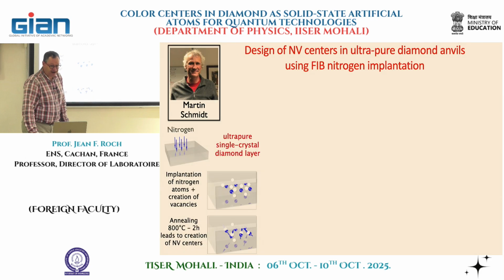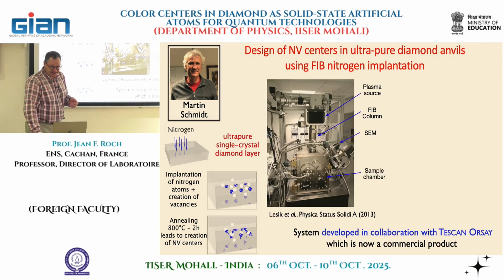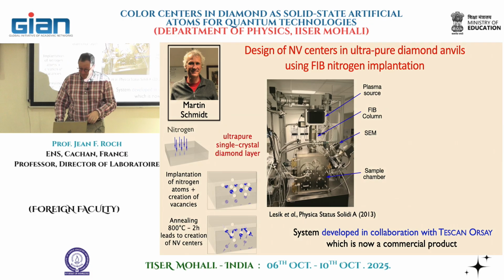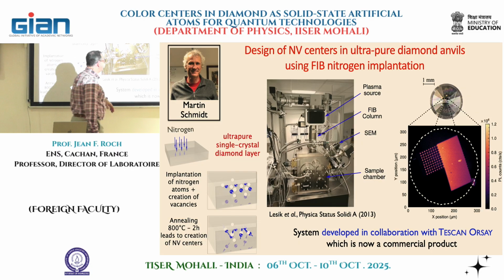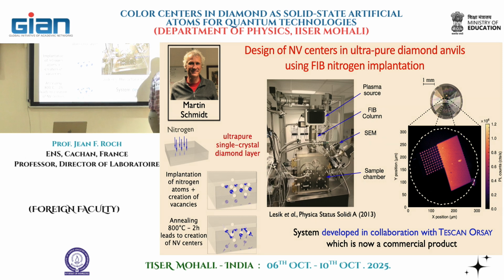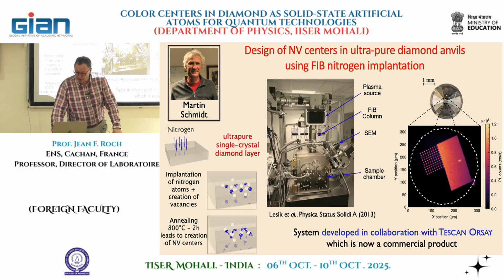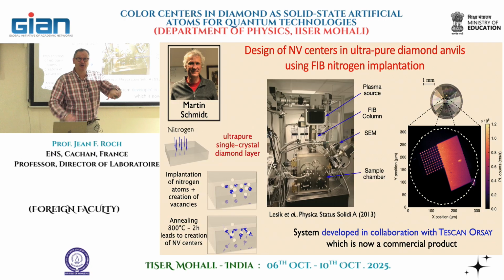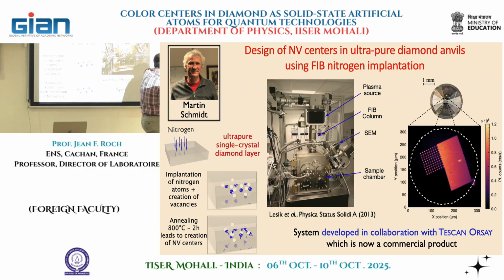So what I want to do now is to show you how we implement this very simple idea. And the very first thing, we have to create the NV centers. As I mentioned, we have this remarkable tool developed by Martin Schmidt in our team, where we can implant the nitrogen atoms and convert them into NV centers. And you have here, on an anvil tip of a diameter of 300 micrometers, arrays of NV that were produced with a pitch of 10 micrometers. Each NV dot has a diameter of 2 micrometers in this experiment, or just a layer of NV with uniform density that can be used for wide field NV magnetometry, as I showed you before.